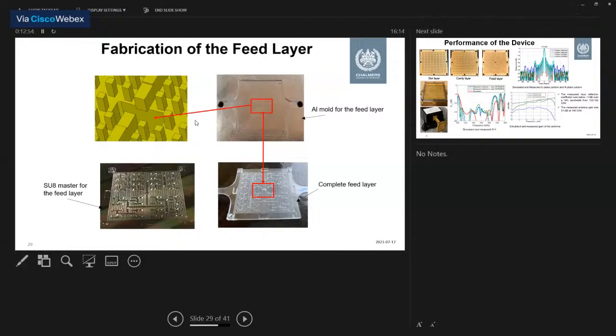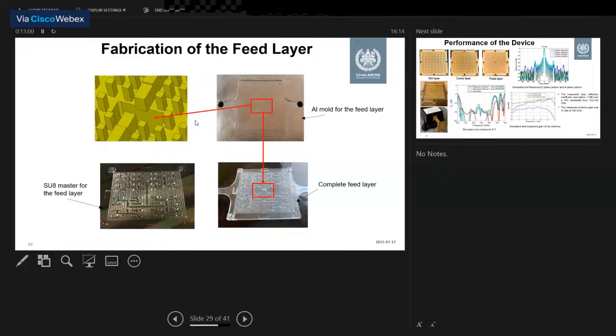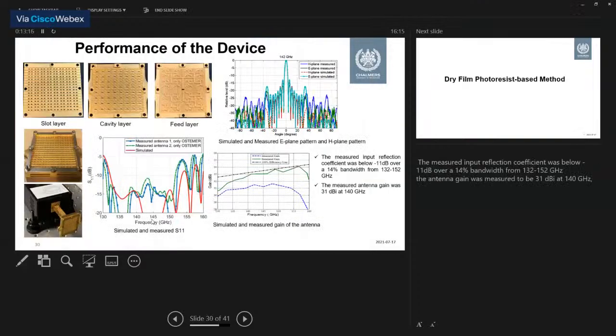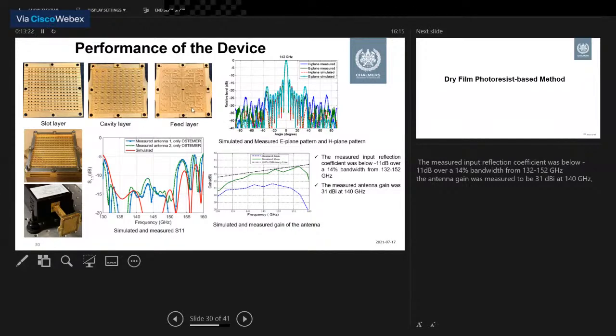So the purpose of showing all of these layers is that you can design the aluminium mold, requiring the geometry that is needed, and then you can easily transfer the design by combining it with the PDMS mold. So these are the fabricated pieces: the final slot layer, cavity layer, and feed layer. And from the measurement result, you can see the measured input reflection coefficient was below -11 dB over 14% bandwidth. And the measured gain is 31 dBi, which is very good at this frequency range.